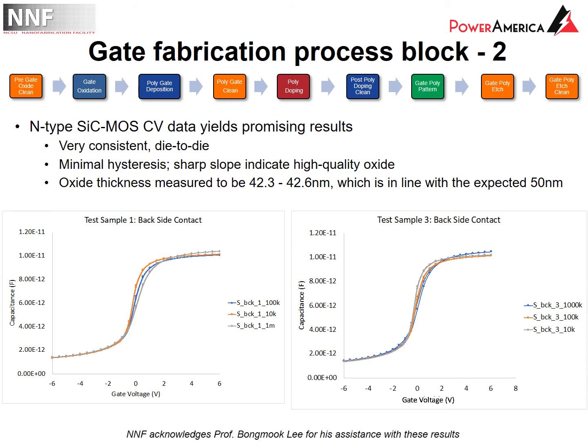First of all, as you can see from the graphs here, the results of the CV graphs are very consistent, die to die. There's minimal hysteresis. There's a very sharp slope, which indicates high quality oxide. And again, we were able to hit the thickness right in the range where we wanted it. We got anywhere from 42.3 to 42.6 nanometers in thickness, which is very well in line with the 50 nanometers that we were expecting.